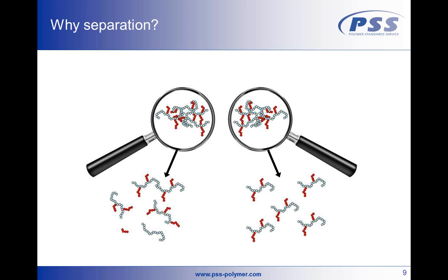However, if we look carefully, like we do here, if we separate our samples, then we see that obviously both samples are completely different. In the one sample, you have quite homogeneous structures, all of identical structure, here on the right-hand side. And on the left-hand side, you have a quite heterogeneous structure. You have backbone chains which are not grafted, and you have free grafts and so forth, and you have different grafting efficiency on the chains. So the average composition and the average molar mass can be determined by standard methods like NMR, and the molar mass by light scattering, osmometry, and so forth.